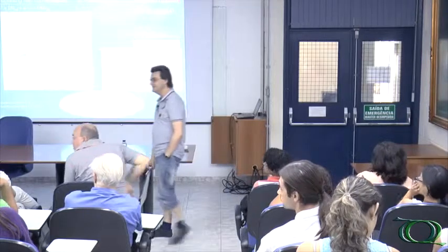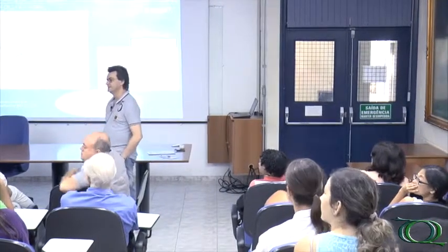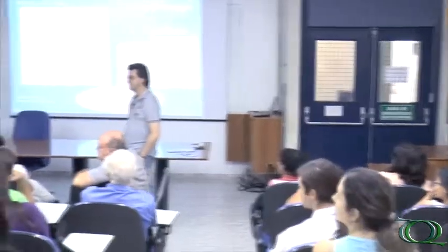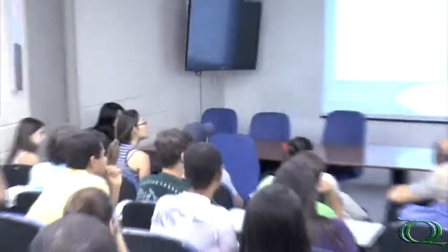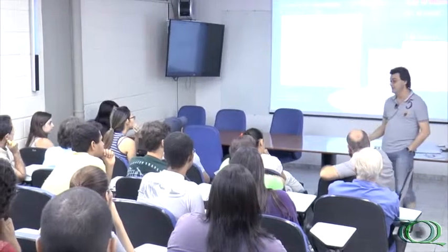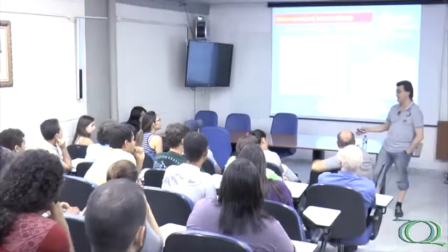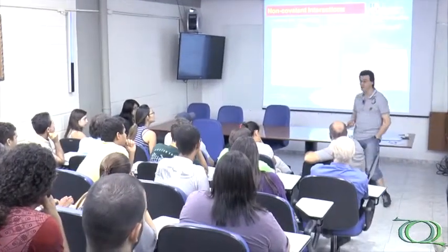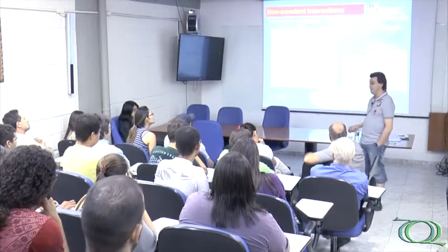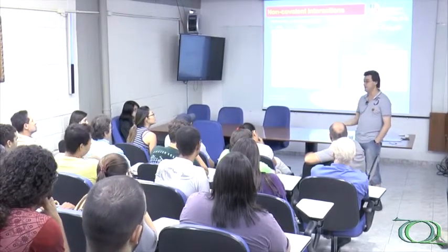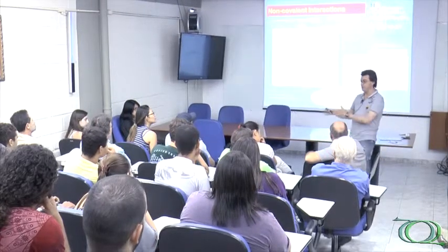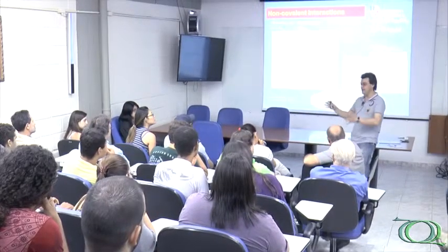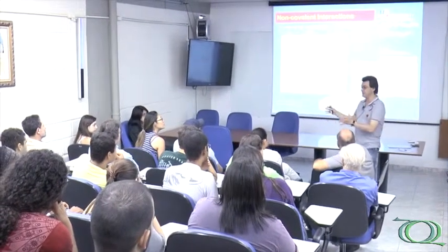The last experiment that you were doing with the fourth year student, are you planning to change the design? Yes. Actually, my initial idea was to do the experiment with potassium, because we know that potassium has a bigger effect than sodium. But we used sodium because the solubility of potassium perchlorate is much lower. And we wanted to make buffers, and initially we wanted to keep the cation concentration constant.